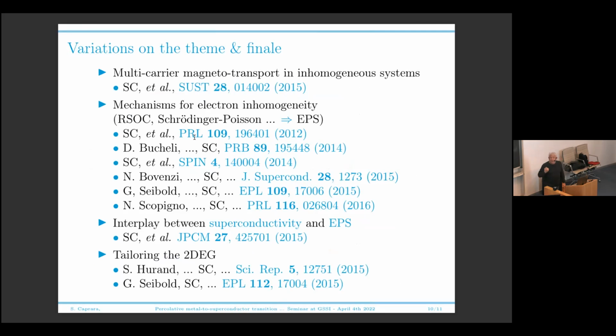Of course, we asked ourselves, why is the superconducting system inhomogeneous? And we came out with various proposals. All of them are essentially based on the idea that for some intrinsic mechanism, your electron gas is unstable against electronic phase separation. In your system, you tend to segregate regions with slightly larger, you don't need it to be very much, slightly larger carrier density. It is enough that you start filling the high mobility carrier band to have superconductivity. In other regions with slightly smaller density, you don't have enough carriers to promote superconductivity. And this may easily explain why in your system you have coexisting metallic and superconducting regions.